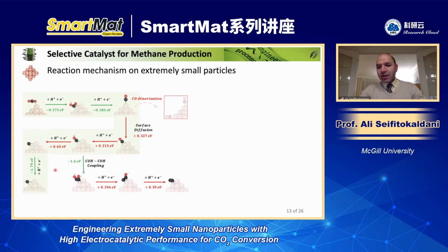There were a few interesting observations. One of them was that the adsorption energy for most of the molecules was much stronger on these particles than on the slab, than on the surface. For example, CO2 often doesn't even adsorb or doesn't even come close to the surface. But under the same conditions, with the same solvent model and applied potential, everything similar, we observed that, interestingly, it can be adsorbed on the surface of the small particles. And that was the same case for ethylene or methane. So we observed different adsorption energy.